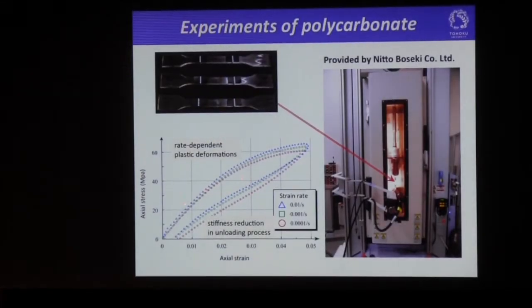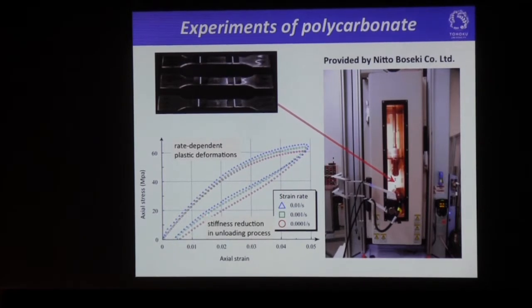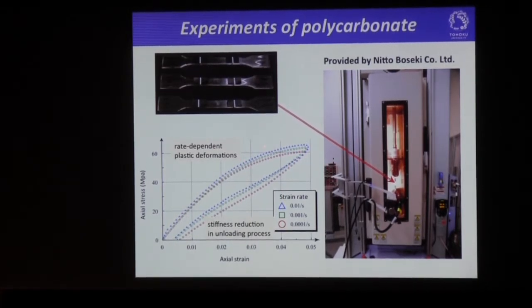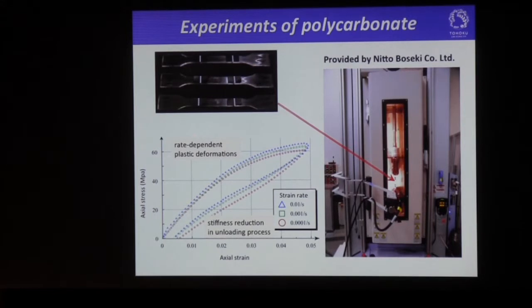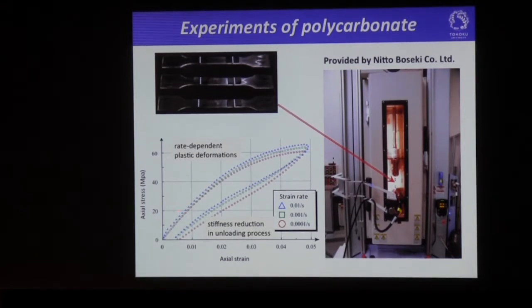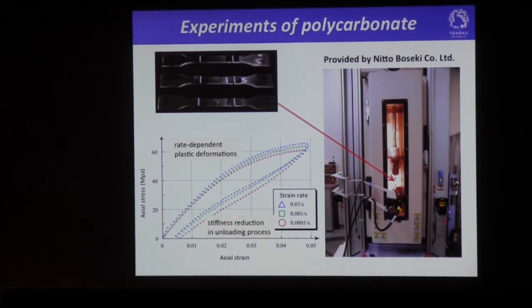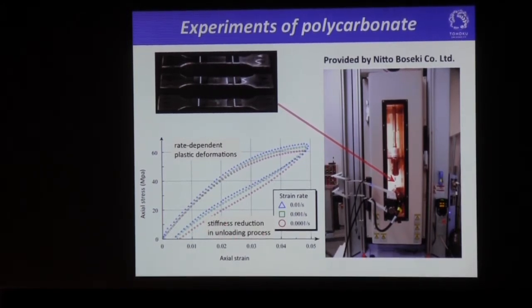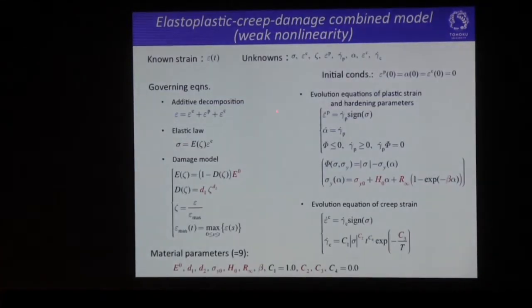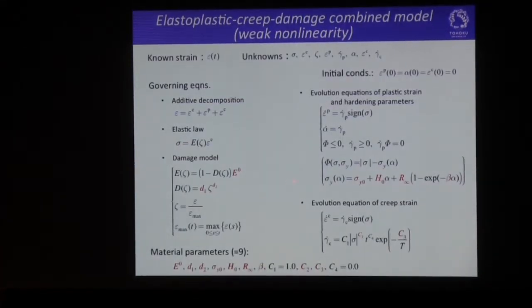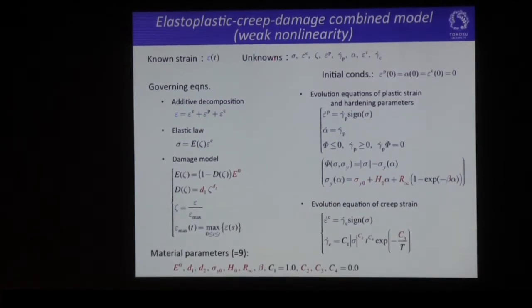This slide shows the stress-strain curve of the polycarbonate matrix, which shows weak nonlinearity. As you can see, rate-dependent plastic deformation can be found. At the same time, we can see the stiffness reduction in the unloading process. So in order to represent this kind of material behavior, we introduce this constitutive equation, that is the elastoplastic creep damage model that exhibits weak nonlinearity.